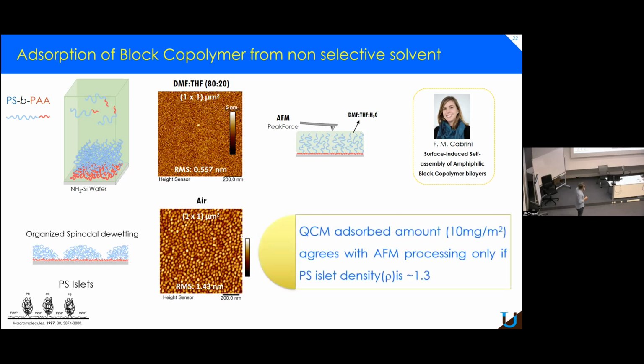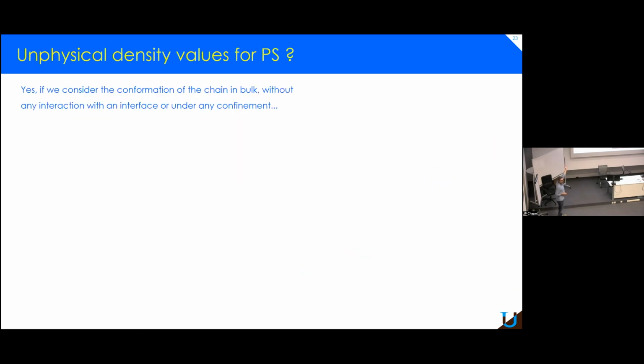And so what we did is that we measured the mass, or the density if you want, adsorbed here using QCM and also from AFM imaging. So we were able to count the number of blobs to measure the volume. And to make the two experiments agree together, we had to put in a value of density above 1.3. So this was just another piece of evidence for us that somehow polystyrene, when it's confined, the density seems to be higher. Okay, but I agree that this was the big question, the unphysical density value for polystyrene. Many people told us that.